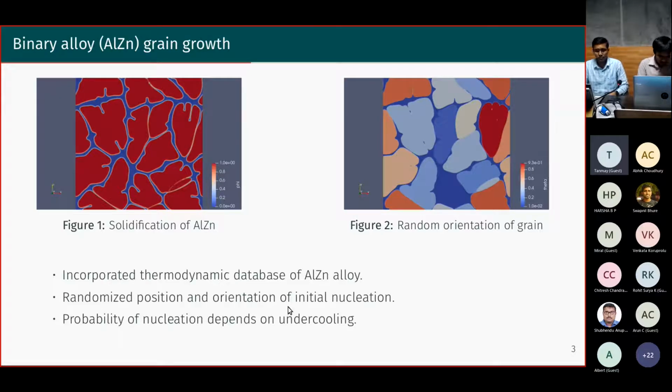I would like to add just one more point. So here this is the theta field, and you might be able to see that we have a scale which says that in different grains we have different theta values. So in this grand potential orientation field based model, each grain is represented by a theta value. In a grain the theta value will be constant, and then we will have different grains with different theta values. That's the major difference between any multi-phase field model and orientation field based model.